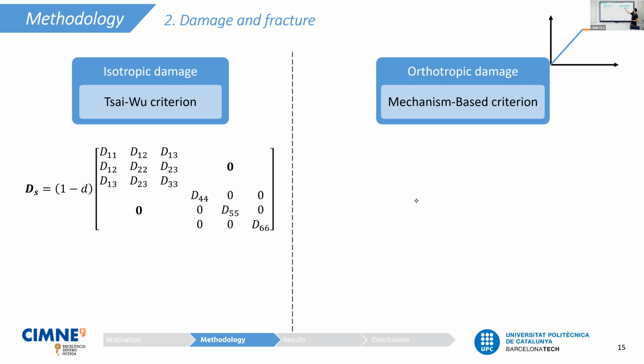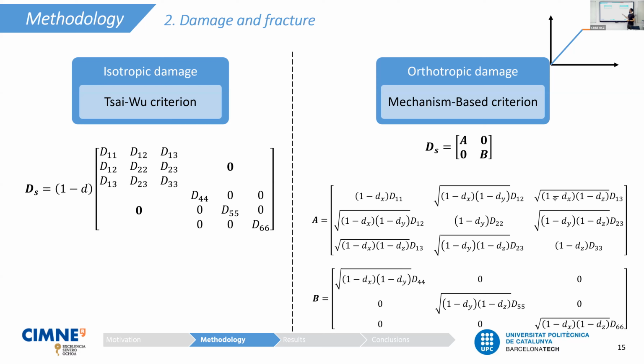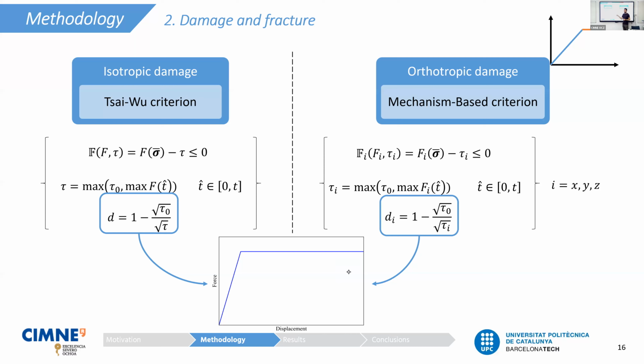However, since for the mechanism-based criterion we have one stress factor different for each component, we use an orthotropic damage model. In the orthotropic damage model, instead of one damage parameter, we have 3 damage parameters in the X, Y, and Z direction, and these parameters affect the stiffness differently in each direction of the component. This damage evolution law follows the Kuhn-Tucker consistency conditions, and it is a perfect damage law, meaning that neither hardening nor softening is considered.